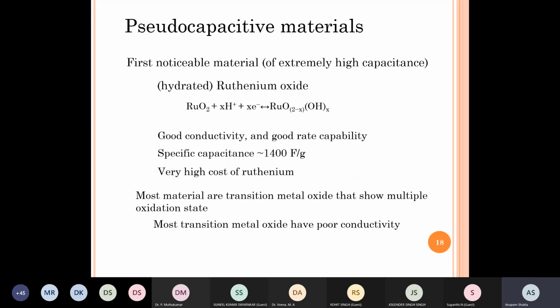For pseudocapacitive material, the first noticeable material of extremely high capacitance was ruthenium oxide. It was the hydrated form of it, something that we saw earlier. This is one of the rare pseudocapacitive materials that also has good conductivity, and therefore shows very good rate capability and a very high specific capacitance of 1400 farads per gram. However, it could not be commercialized because of the very high cost of ruthenium.